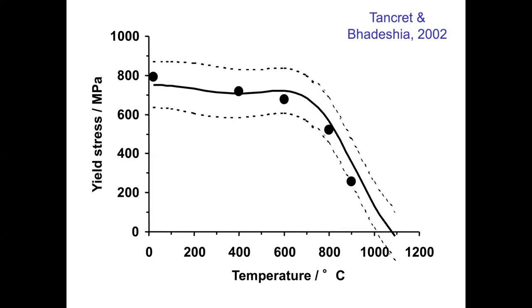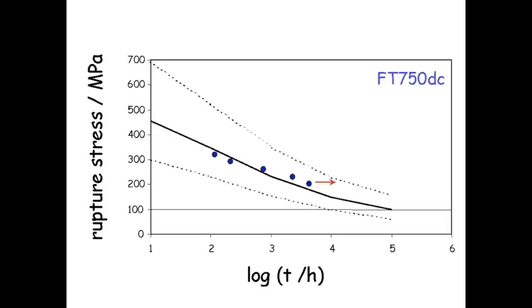Creep strength is really important, right? And you can see that our modeling uncertainty is very large here. And this is the predicted curve. And we are not worried about the fact that the modeling uncertainty is large because other metallurgical data, for example, the microstructure and so forth, tell us that this should be able to resist a stress of 100 megapascals at 100,000 hours. That's the typical 100,000 hours, which is more than a year, right? So you can't do these experiments and then say, okay, you have to wait for 5 years before we give you all the data. So this is predicted, and these are experimental data, and these tests are ongoing, but actually this is quite old work. So we have really long-term creep data on this.